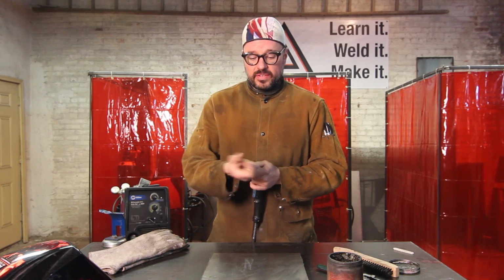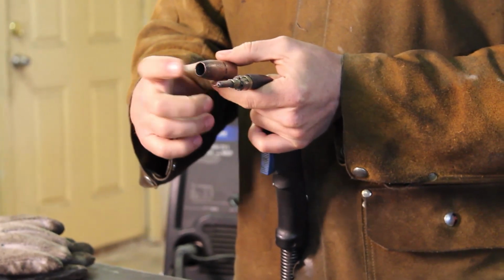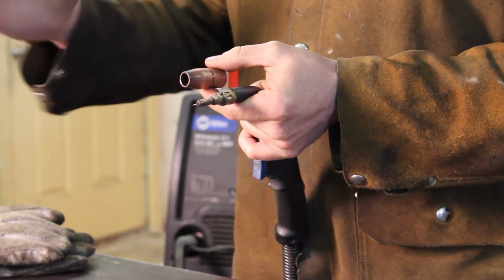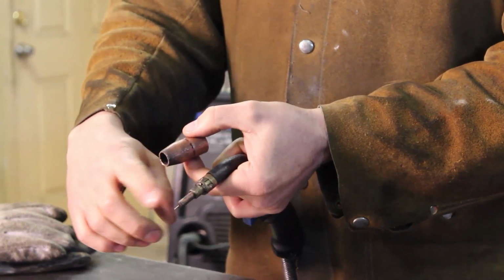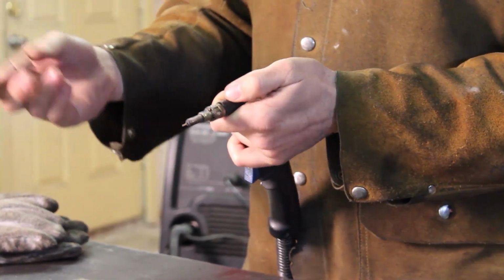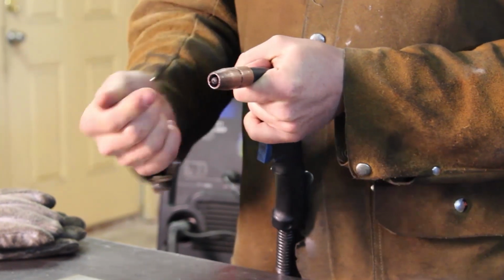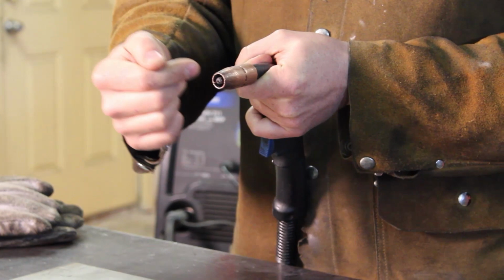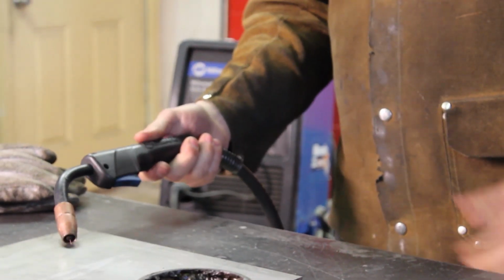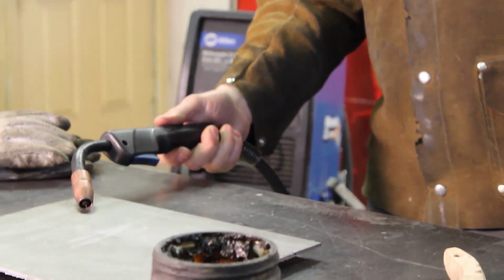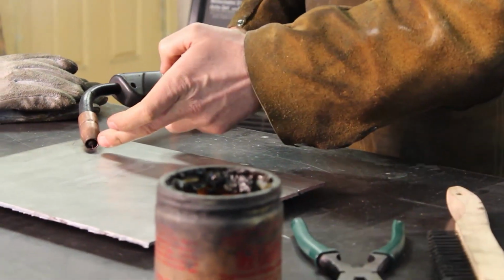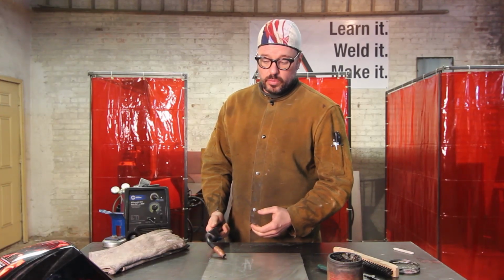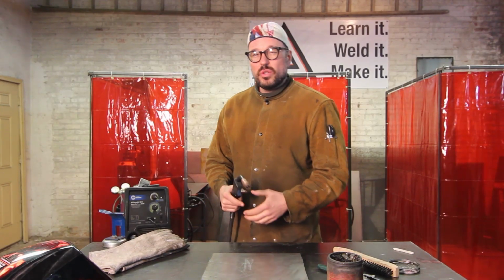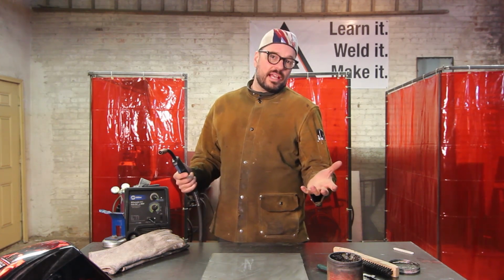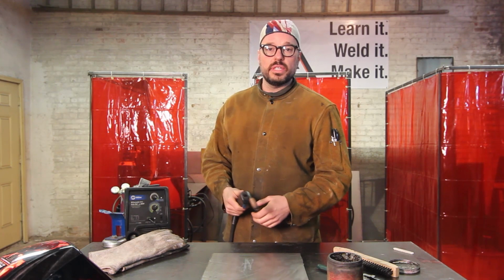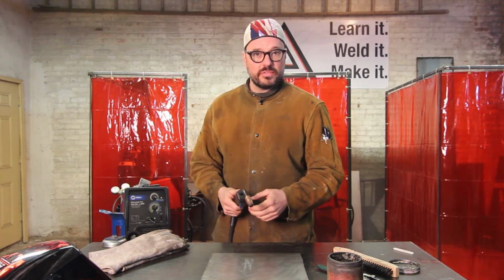So if you get buildup onto your nozzle and onto your contact tip, what happens is, on most machines, your contact tip is live. Your nozzle usually is insulated from the current going through it. But if you build up a conductive metal bridge in between your contact tip and your nozzle, and you go through your weld zone and accidentally touch down, this is going to lead to what's called double arcing. You're going to have an arc point at the edge of your nozzle and of course at your electrode wire. At higher voltages, 1 out of 10 times you're going to actually weld your nozzle to your piece. And that's not good because these are a little bit more expensive than contact tips.